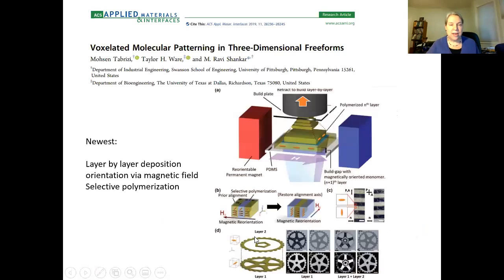There's yet a newer way. This was published in 2019. Ravi Shankar, working together with Taylor Ware. Ravi is at the University of Pittsburgh. And so what they did was a layer-by-layer deposition of a very thin film of, again, a non-polymerized liquid crystal elastomer. And then they used a magnet to orient the director in the unpolymerized material. And then they selectively polymerize different places. So they can make objects of different shapes, and they'll have essentially 3D control of the director in each voxel. So there are going to be more and more interesting ways to pattern these materials.